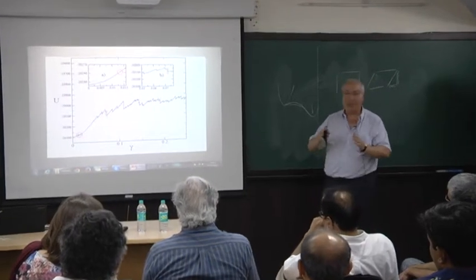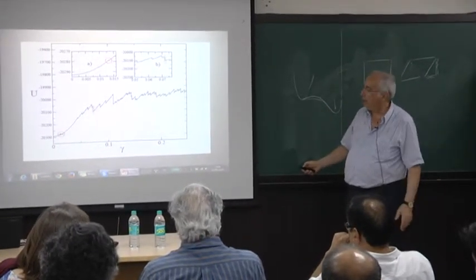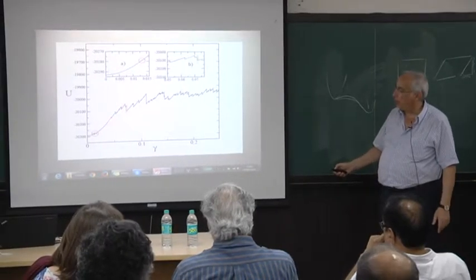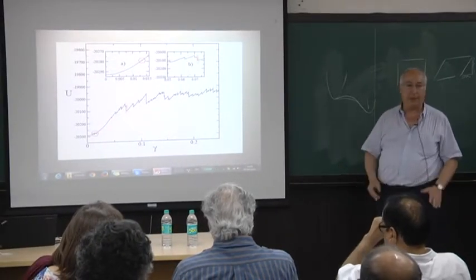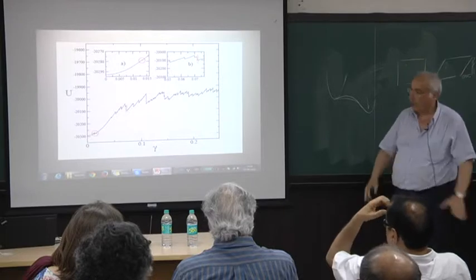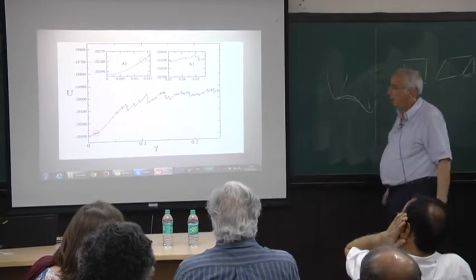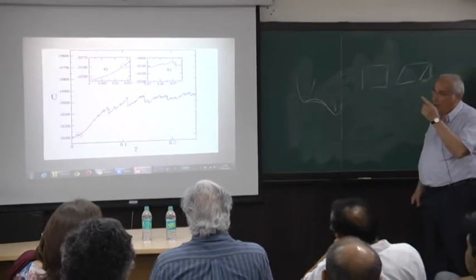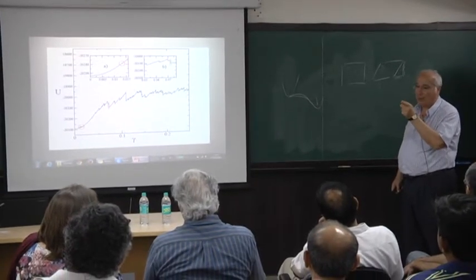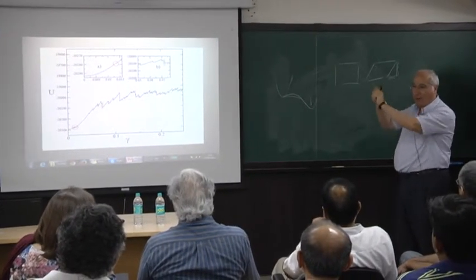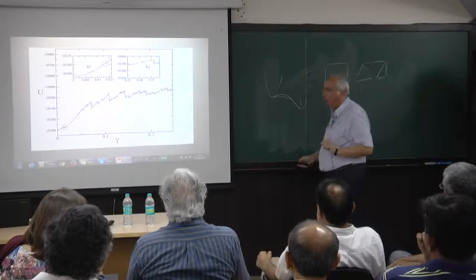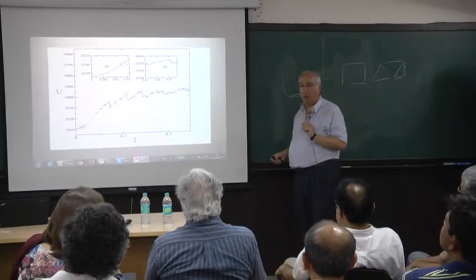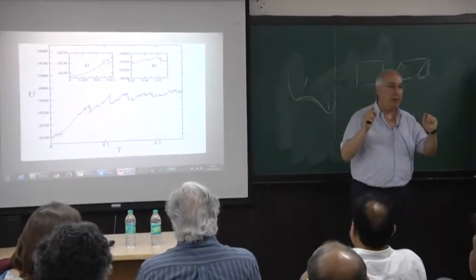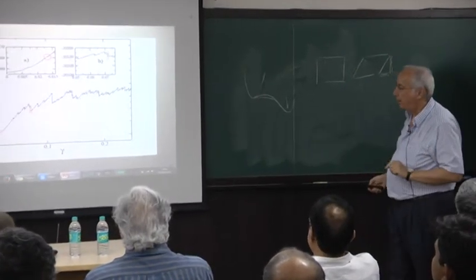If you do now system size analysis, the average stress drops in this region are system size independent. So they are really localized. Now, localized here is not in the sense that we discussed today that the event has a power-law decay, but the amount of stress drop or energy drop is system size independent. So it's a very precise statement that one can make.